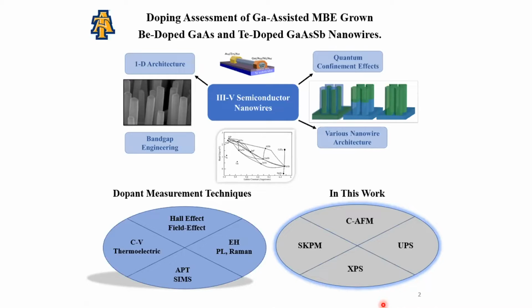Statistical analysis of all four measurement techniques have provided evidence for confirmation of incorporation of beryllium and tellurium in gallium arsenide and gallium arsenide antimonide nanowires. Hence, these surface analytical tools without contact fabrication are found to be a very successful and powerful tool for direct measurement of the dopant incorporation and doping levels in nanowires.